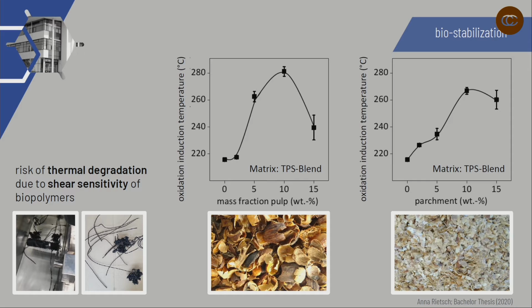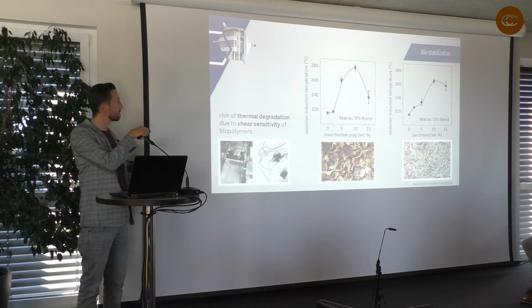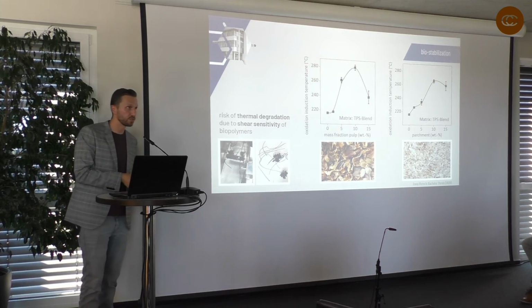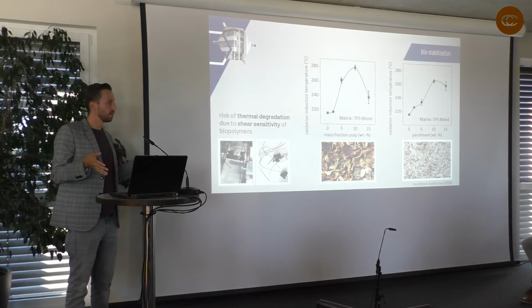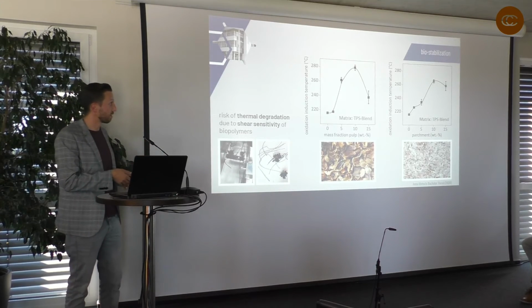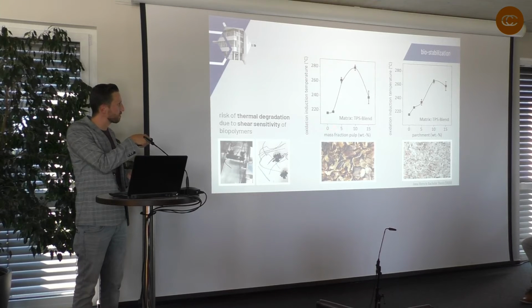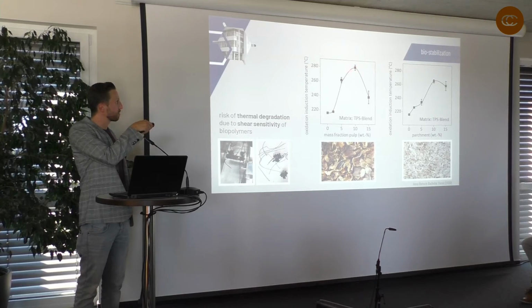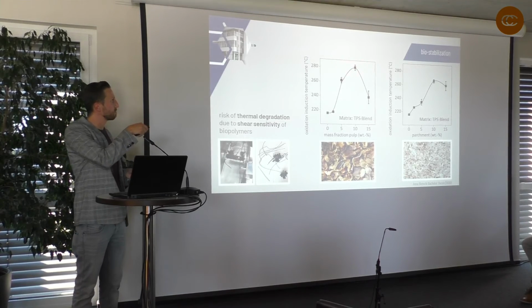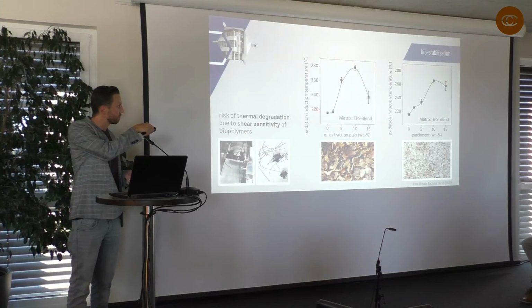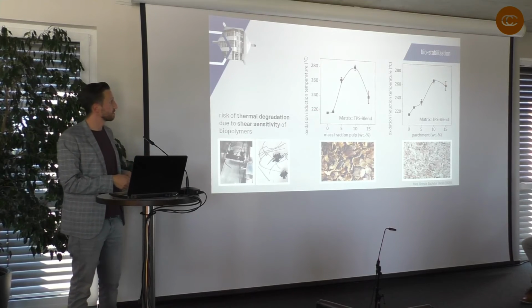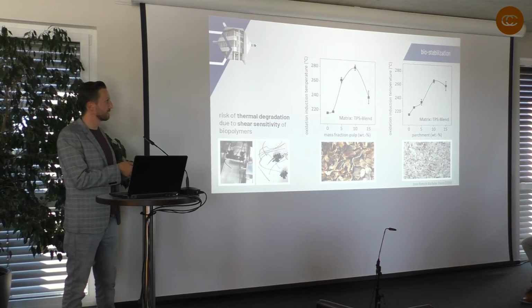What you can see here is the concentration of, for example, the pulp and also the parchment, in dependence on the degradation temperature. So this temperature, the oxidation induction temperature, is the temperature when the degradation of the biopolymer master batch starts. What you can see is that with an increasing concentration of our coffee byproducts, this temperature is rising. Here we reach a maximum, from 220 to 280 degrees Celsius.